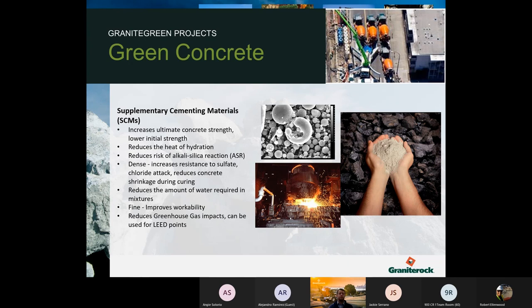It's better for concrete to have less pores or capillaries. The reason being is materials or chemicals can transfer through water and get into the concrete. So by creating a more dense concrete, you're inherently reducing the sulfate, chloride, and other attacks. Using SCMs can reduce the amount of water required, which is good, and it also improves workability. To top it off, using SCMs can help with LEED points.